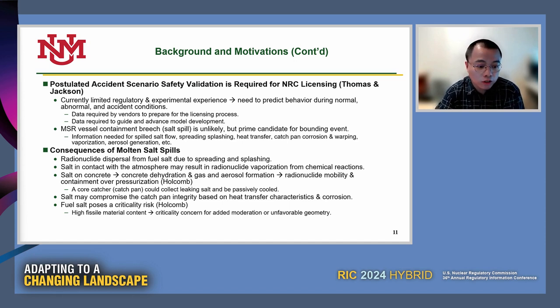Radionuclide dispersal from fuel salt due to spreading and splashing. Salt in contact with the atmosphere may result in vaporization, and the chemical reaction of salt on the concrete can degrade the concrete. Then the salt may also compromise the catch pan, which causes catch pan deformation or corrosion, and which will potentially lead to leakage. And then fuel salt can also pose a criticality risk. Those we can find in Dr. Holcomb's technical report in the reference.